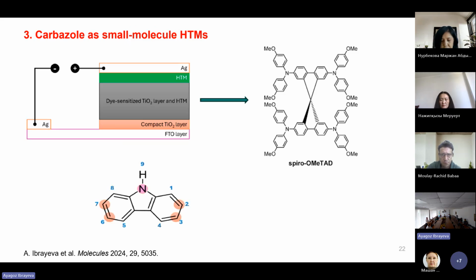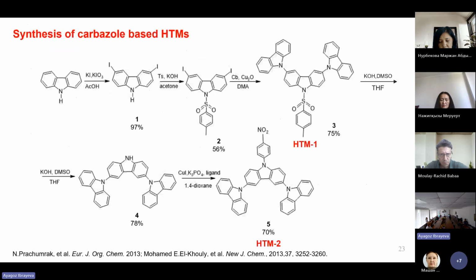That's why we offer carbazole, which has advantages such as being electron-rich, having tunable energy levels, and good thermal and chemical stability, and we can easily synthesize other carbazole derivatives. For this aim, we carried out some syntheses. On this slide, we show the synthetic route for HTM1 and HTM2. First of all, we carried out a halogenation of the carbazole. We put iodine at the 3 and 6 positions and obtained product number 1 with a 97% yield.